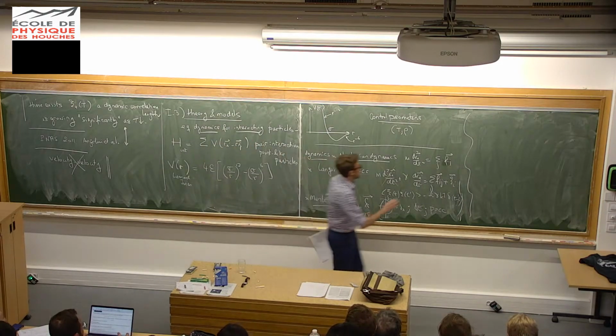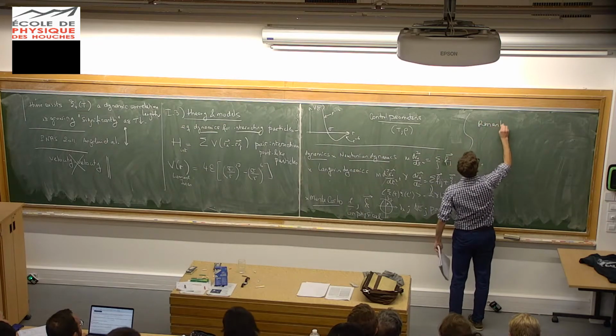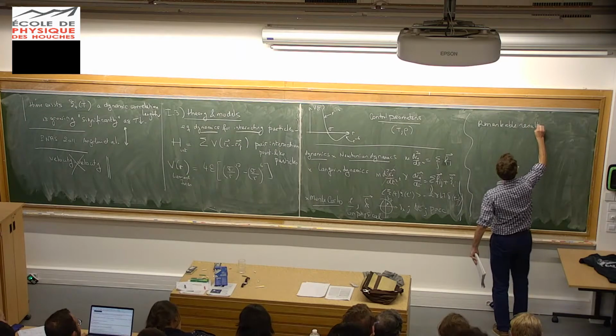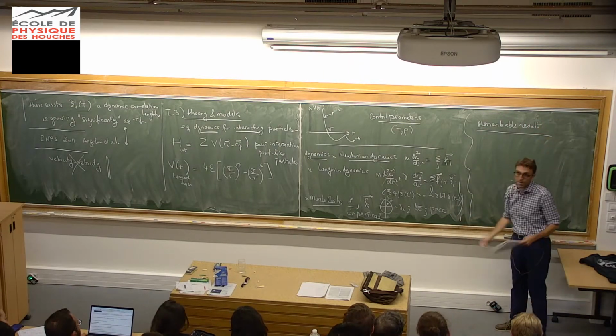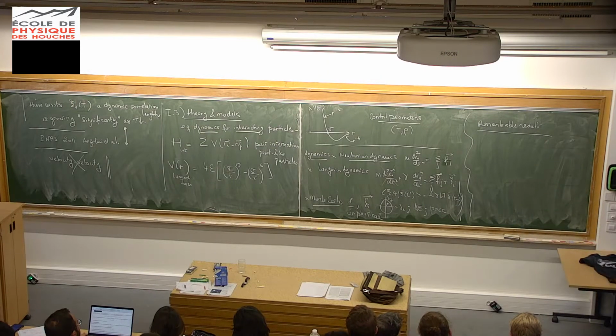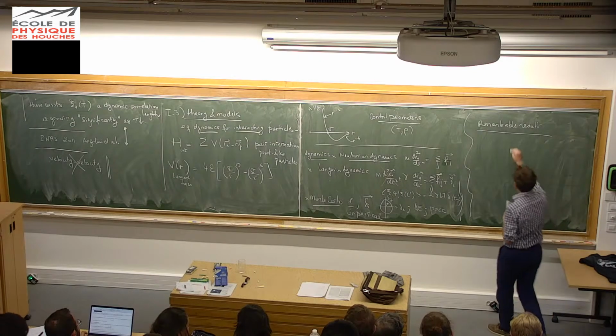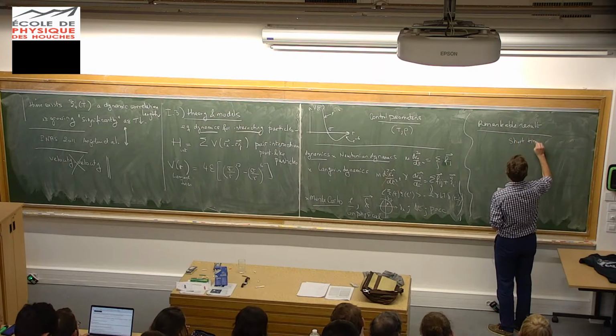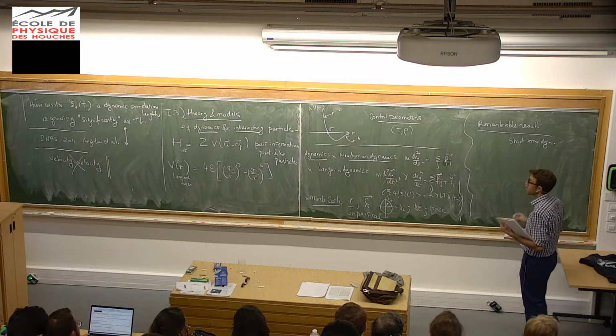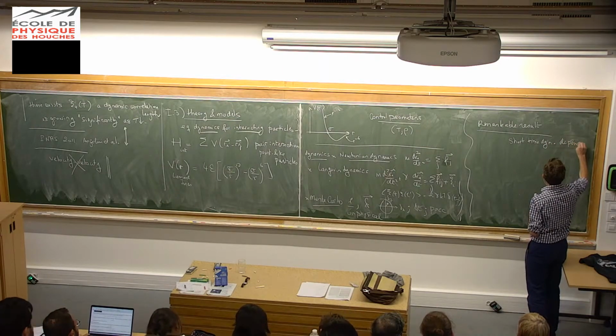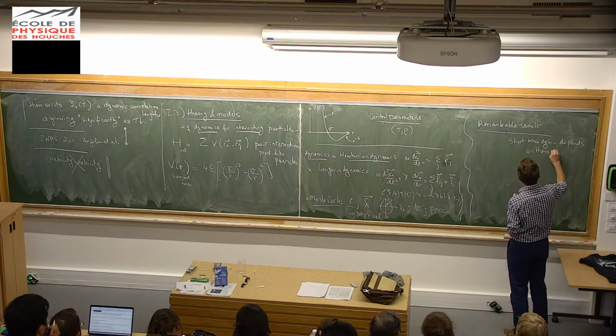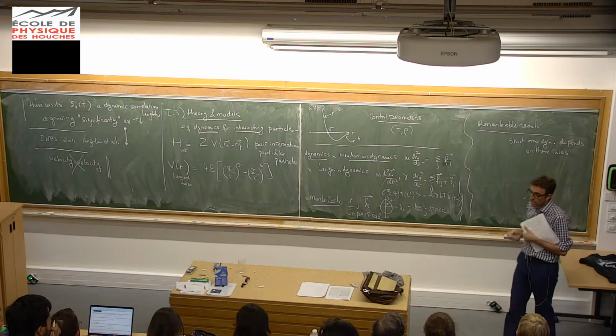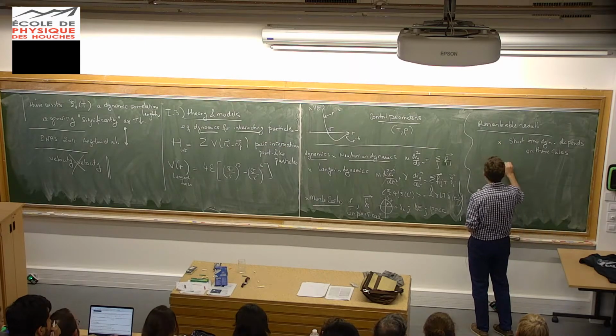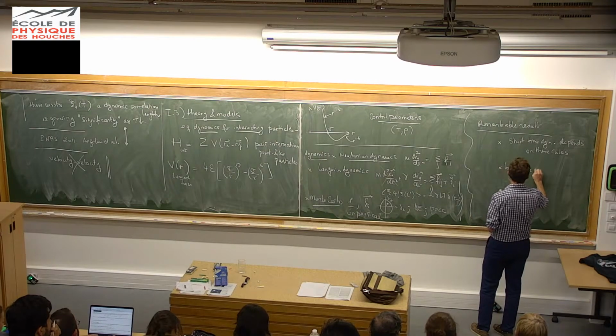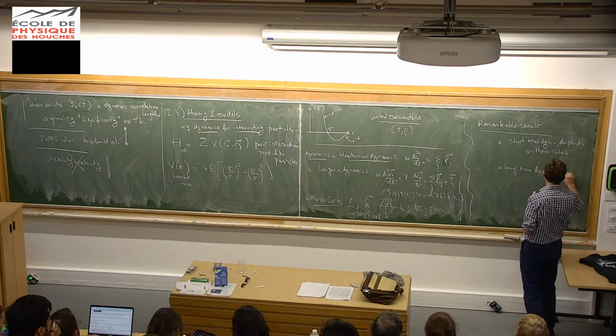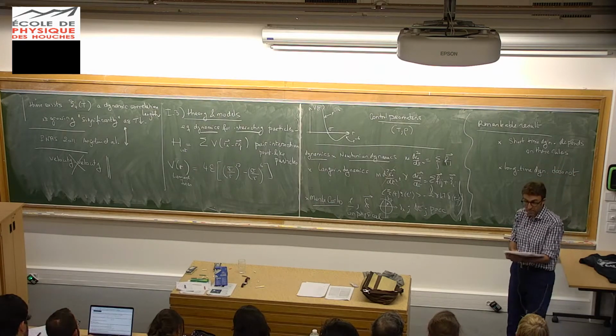But the remarkable result that I'm about to expose. So again, I should insist, because this all respects the rules of equilibrium, you'll have the same thermodynamics and static properties. But the result is that if you look at the dynamics, the short-time dynamics really depends on the microscopic rules. So the caging, the short times, it does depend on the microscopic rules. But if you look at the long-time dynamics, it does not.